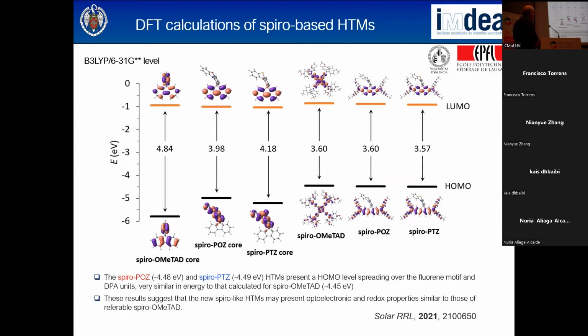I will not go very much into detail, but you can see that this is the central core without the arylamino units. And here it is the same for the spiro. So these are the orbitals for the HOMO. But when you have our molecular spiro with the phenoxazine or phenothiazine, you see that the HOMO is now localized on the heterocycle moiety, not here like in this. And this is the reason the energy level is increased here. The LUMO is basically the same and is located on the fluorene moiety.